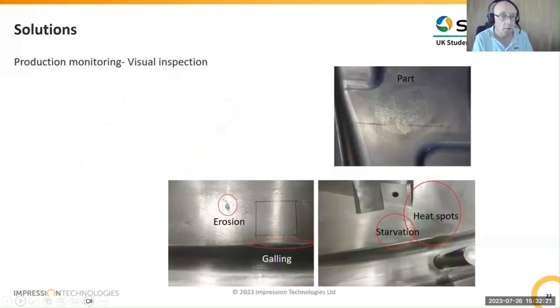Next one, please. Looking at parts and the dies, in the top right there is a part where you can see there's a slight surface defect, which is sometimes referred to as orange peel. What's happened in this instance is that although there's not a lot of obvious metal movement taking place in there, the lubricant is pooling in that area, and having a solid lubricant component that is then acting as an insulator so that the part doesn't cool properly in the quenching operation in the cool dies, and you get this surface defect occurring. What we need to do in that case is either remove the lubricant buildup in that area, or ensure that we're not spraying lubricant in the area where it's not needed, so it doesn't migrate into there.